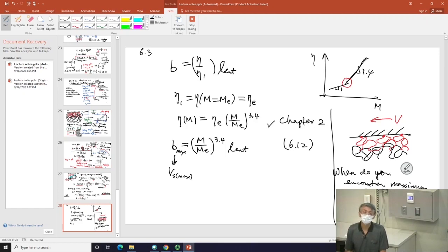So in that limit, of course, you don't cause them to decouple. Not very strange. So Wi smaller than 1 is not going to do it. However, if I say Wi equals 50, is that going to give you maximum slip? Or equals 500? When does it give you maximum? It turns out that is yet a question to answer.